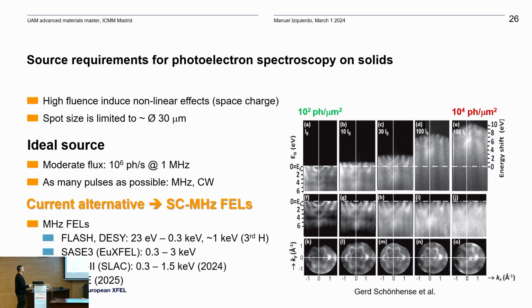So what is the possibility? The possibility is to do these experiments at moderate flux, in the order of 10 to the 6 photons per second, and to have as many pulses as possible. Ideally, you want a CW source, and if it's megahertz, even better, like in a synchrotron. Currently, there is only one alternative, superconducting accelerator FELs, because those are the only places where you have a megahertz repetition rate. These experiments were tried at SACLA, running at 60 hertz, and you can do an experiment, but it takes weeks until you get enough statistics. So currently there are 3 places in the world where this can be done.